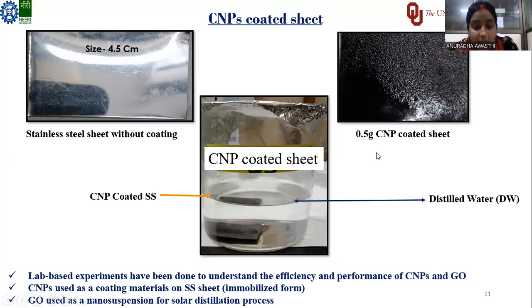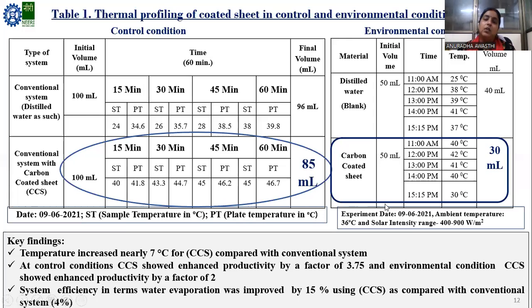So in our application for the solar distillation rejuvenation, we used CNP as a coated material on an SS sheet and GO as a nano suspension for solar distillation application. Here you can see I have taken a small sheet of stainless steel, and I coated this carbon nanomaterial on this sheet, and I put this sheet in the water to check its coating stability along with the thermal performance. So this is the result of thermal profiling of the coated sheet in a controlled environmental condition.